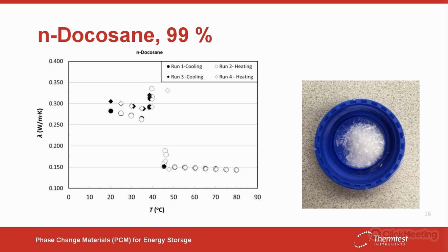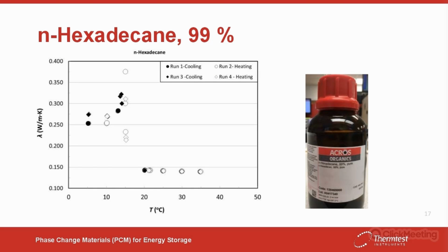And this is because while the fluid was solidifying, it was solidifying in different shapes and not in the same position every time around the wire and between the sample. So some different shapes appear inside the sample.